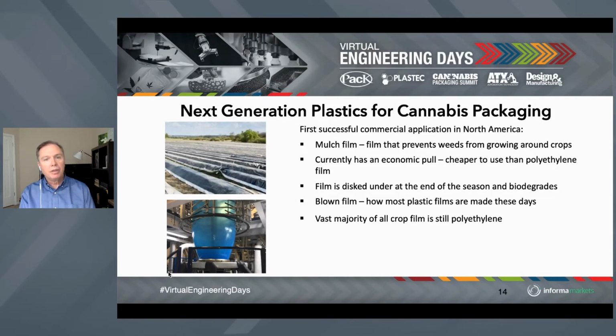So most of these are made through a blown film process where the material is extruded through a circular die, and that's what you see in the lower left-hand corner there. That's a blown film. That one happens to be polyethylene, but materials such as PBAT and PLA mixed together, and others can be blown into films along these same lines. That particular line right there, the material comes out of that annular die, goes up about 3 stories, is collapsed at the top, and then comes back down where it's slit into rolls of material. The vast majority of what you see with regards to the crops, as I stated before, is still polyethylene, but you will see more and more with regards to bio-based materials in the near future.